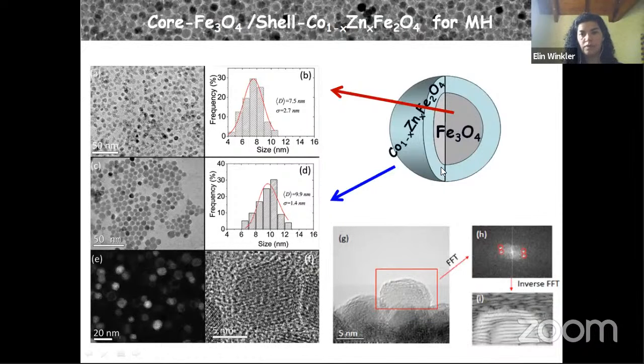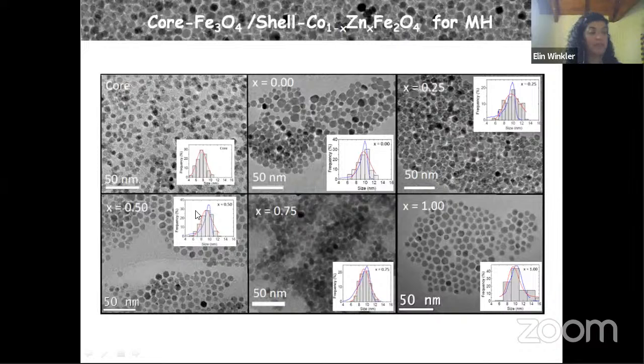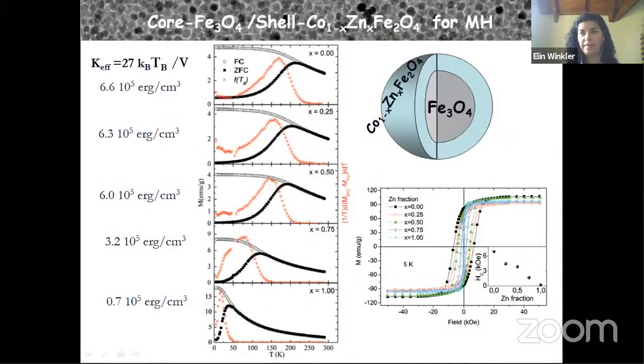Well, here is just to show that all the nanoparticle systems present the same comparable size. And these are the magnetic properties, similar to what we talked about previously. In this case, by systematically changing the stoichiometry of the shell, we tune the coercive field, and this is the magnetization as a function of the temperature, and we observe a change from superparamagnetic to blocked regime, and this maximum is related to this energy barrier, and we can calculate the anisotropy, which changes an order of magnitude when we replace the cobalt systematically by zinc.